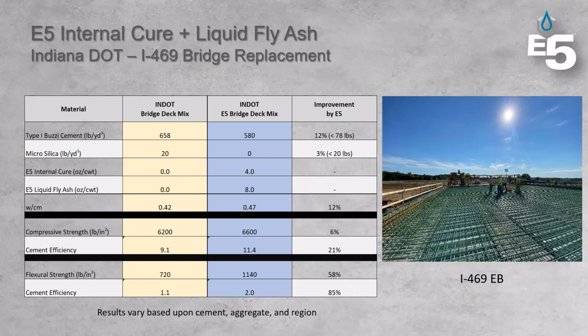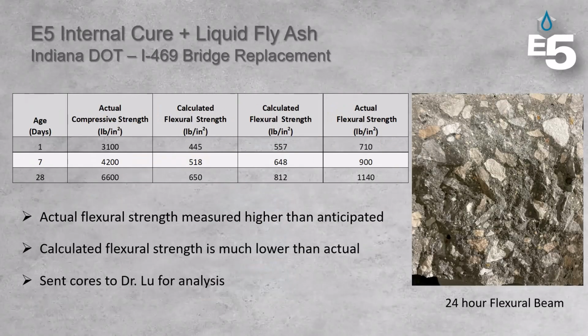And so we were a little nervous that that might have created a brittle scenario or some material out there that might not have been durable. So when we use the ACPA calculations, both conservative and less conservative, to estimate modulus of rupture based on actual compressive strength, you can see that the actual flexural strength was still far above the rest.